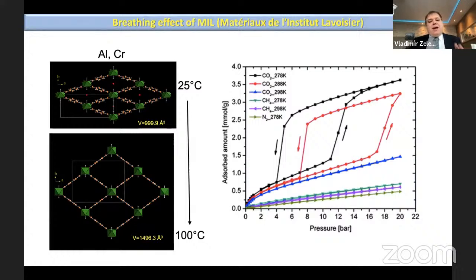In the picture on the right, you can see adsorption isotherms of carbon dioxide, methane, and nitrogen on a MIL compound. And you can see that for carbon dioxide adsorption at 278 or 288 degrees Kelvin, you can observe a big adsorption step and then a desorption step. So this compound breathes. It takes carbon dioxide inside the structure, but not nitrogen or methane. So you can use this process for separation of gases, so-called pressure swing adsorption, and you can separate carbon dioxide quantitatively from the other gases. So this is another possibility of use of these MOF materials.